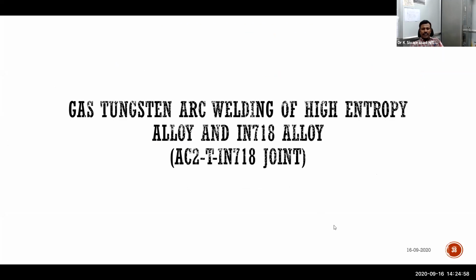And this, with respect to steel and high entropy alloy, we have seen. Now, Inconel 718 and high entropy alloy. Because this is another complex system. Inconel 718 is a very complex metallurgy system. It's a typical best engineered alloy system, people used to call all nickel based superalloys, and Inconel 718 is one such good alloy among them. It has so many alloying elements, almost like 12 to 16 elements in a given Inconel 718, but nickel will be very high, 52%. That is the reason we call it a nickel based superalloy. High entropy alloy is not like that, still it is very good.